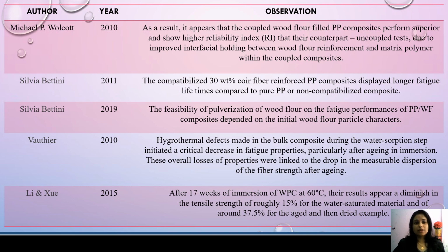Next, Vauthier in 2010 mentioned that the hydrothermal defects made in the bulk composite during the water sorption step initiated a critical decrease in fatigue properties, particularly after aging in immersion. These overall losses of properties were linked to the drop in the measurable dispersion of the fiber strength after aging.